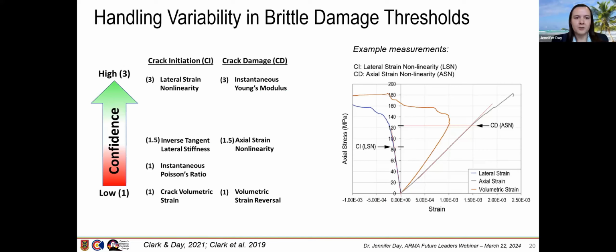When we were doing this lab testing, of course, we measured the stiffness and peak strength, but we also wanted to look at the brittle damage thresholds, so crack initiation and crack damage, CI and CD. There are a variety of ways to measure these properties, as many of you are probably aware. These methods were developed for rocks that were more geologically homogeneous, so free of veins, like the Lac du Bonnet granite and other classical examples like Indiana limestone, etc. So for these veined rocks, what Matt did was develop a confidence ranking of the quality of data we would tend to get from these different measurement methods for CI and CD.